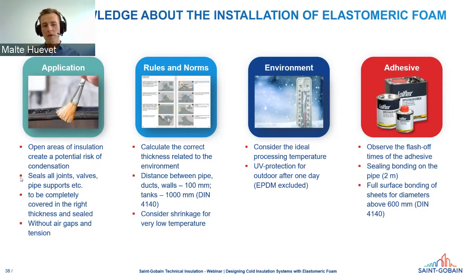Regarding the rules and norms, of course, we must calculate the insulation thickness, especially related to the correct environmental conditions. That's also the most common mistake, that the expectation is that the conditions of the room are always the same. There could be an area where there is not that much airflow, and then the problems will start, because the system itself may be correctly calculated for insulation thickness, but in some certain areas there is less air circulation, and then of course the minimum insulation thickness is not thick enough, and condensation starts.